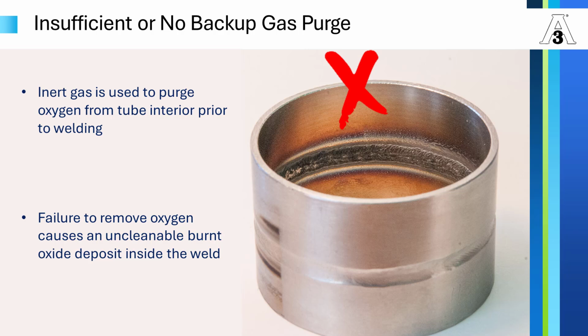On the other end, you're going to put something to provide back pressure so you can provide some level of pressure inside that line. Now, at every one of those tack welds, you're going to leak argon out. So you've got to know how much volume of argon you need to fill that line and keep it filled, and then you've got to wait till it gets filled. People get impatient. Oxygen is lighter than argon, and so it goes to the high point. And so you start welding too early, and on your line up here, you've got oxygen still sitting there in the top of the line because argon hasn't been moved through at a high enough velocity or had enough time to remove all the oxygen. That's usually how this happens.